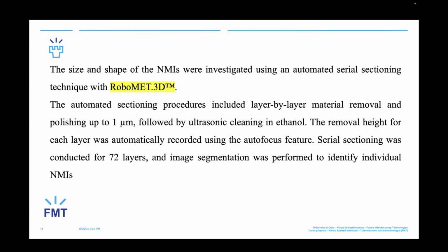At the Forschungszentrum in Germany, we used this new microscope called RoboMet.3D. This new technique detects non-metallic inclusions or any defect in cast material using a robot. It performs mechanical polishing; for example, you can order the robot to make 10 micrometers of mechanical polishing, then take a picture, and then the robot goes back.